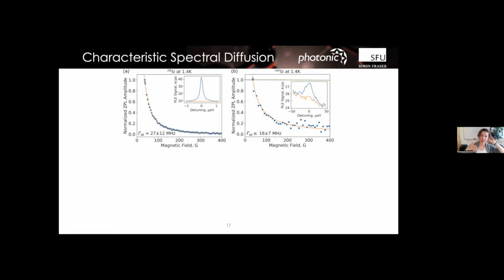Because we know that the spectral diffusion, which is the tendency of an individual color center to wander in frequency, right? We know that it's pretty good in silicon-28 in these bulk, like pristine environments, because we see these really, really, really sharp lines as an ensemble. And you can also look in and burn in and get really, really narrow lines. So we did this kind of characteristic spectral diffusion test where we swept a magnetic field and saw how quickly we can hyperpolarize as a means of doing a quick and dirty test to assess the quality of the material that we had.